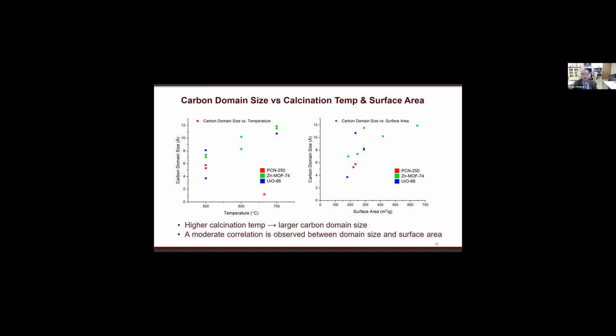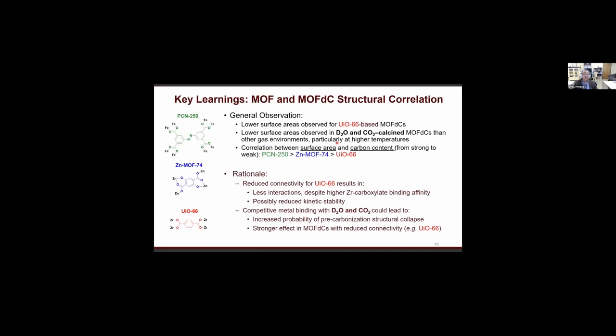And also carbon domain size versus calcination temperature and surface area. There's a kind of a correlation here. As the temperature increases, the larger the domain size, which we already talked about. And also there's a rough correlation: as the surface area increases, the carbon domain size increases as well. So a moderate correlation.